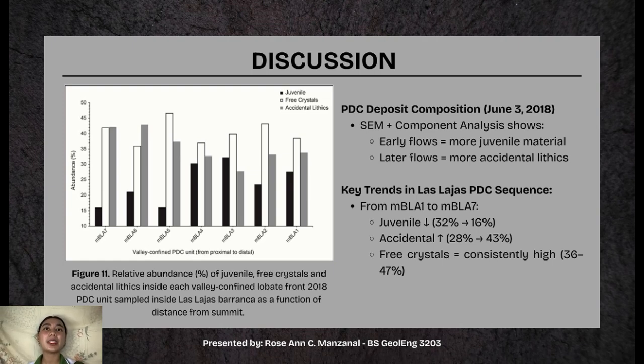In the earlier PDC units from the June 3 eruption, we see a dominance of juvenile clasts, like black scoria and fresh glass, but as the day progressed, later flows, especially from 330 onward, show a shift toward older, reworked material, oxidized and altered glass from past eruptions. This suggests that early flows erupted fresh magma, while later flows were more destructive, pulling loose debris from previous deposits on the steep upper flanks.